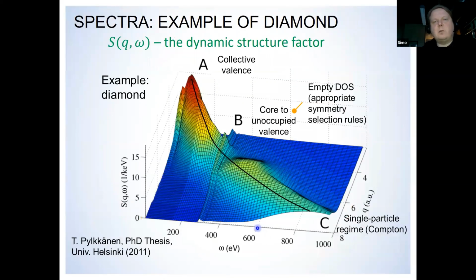But actually the spectra look a bit more complex than that. The spectra are encoded in S(Q, omega), which is the dynamic structure factor. And this is a simulation of how the spectra would look for diamond. We chose a particularly simple system, just carbon atoms.